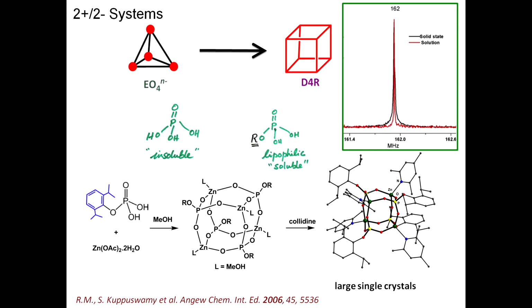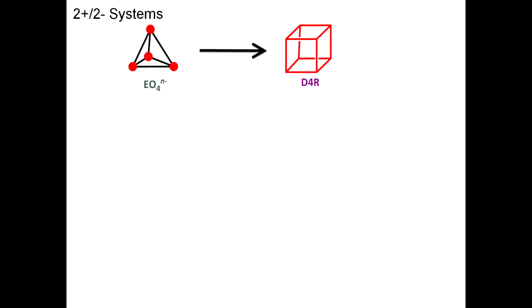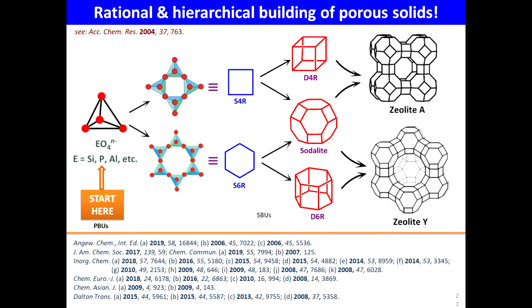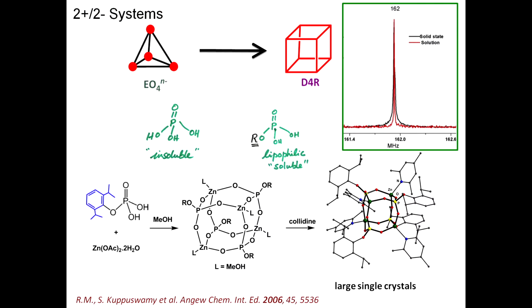So we could immediately form this double 4 ring, which I showed in the previous cartoon as one of the fundamental building blocks most often encountered in zeolites. Okay, now this is what we have here. We made this compound, so essentially it's a cutout of a zeolite, other than that the 8 corners have been capped by organic terminators. Here is a 2,6-diisopropyl phenoxide, and here L is nothing but methanol, which is used as a solvent. Zinc is essentially tri-coordinate. The fourth coordination has just been compensated by a loosely hanging methanol, which can be kicked out by bringing in a stronger Lewis base such as collidine, which is 2,4,6-trimethylpyridine.